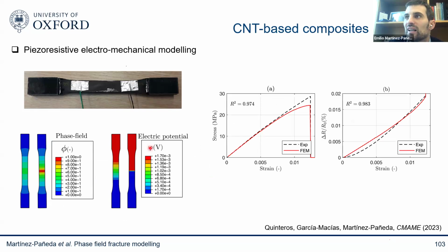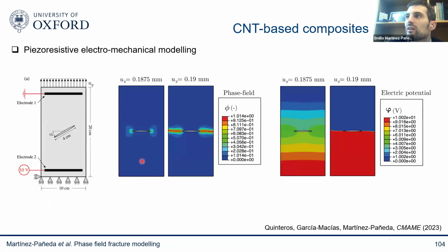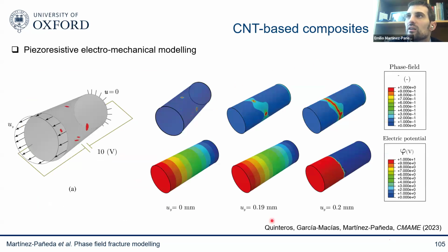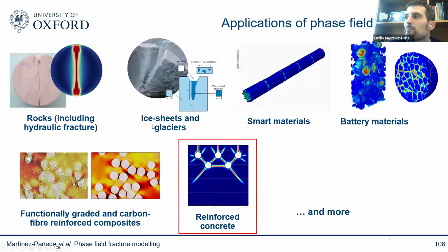You can see the phase field and the electric potential. So now we know a crack has propagated. There's this discontinuity in the electric potential, and we can do that in many different problems, different crack orientations, and even in 3D components where you may have multiple defects, and eventually you get this kind of piezo-resistive electromechanical behavior.